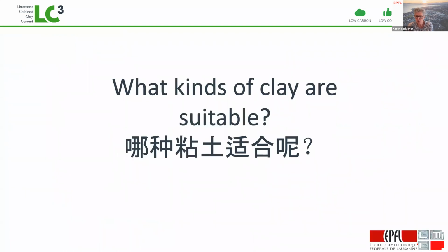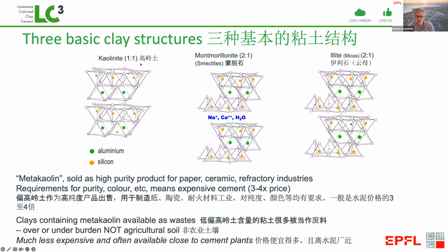Now, the first question is, what kinds of clay are suitable? We need to have some of this mineral kaolinite. This is a 1-to-1 clay, which has layers of silica and alumina. And when it's calcined, this structure becomes disrupted, and both the silica and the alumina are available to react and form hydrates. But we don't need high-grade metakaolin. We only need clays which are often available as wastes, which contain a much lower amount of kaolin.